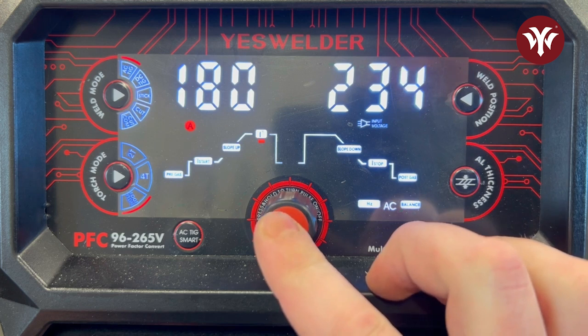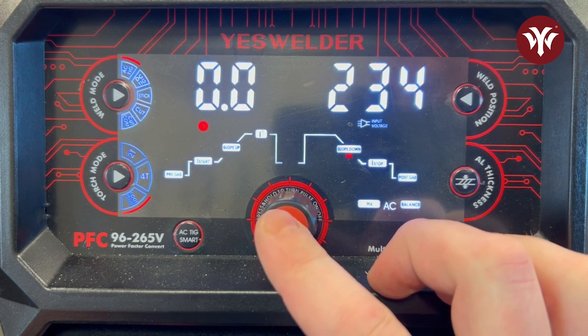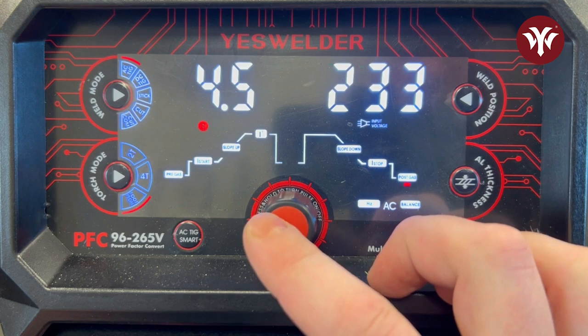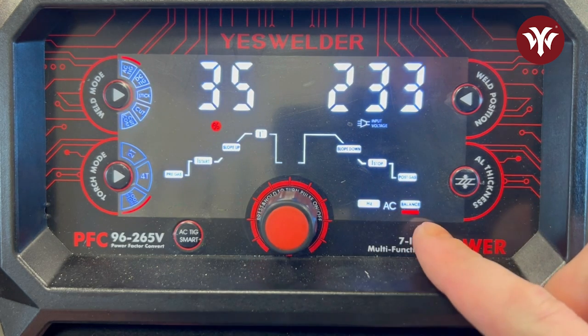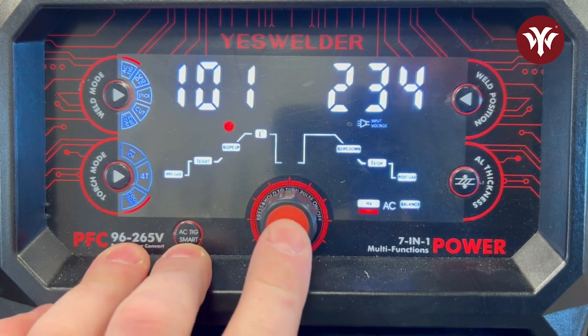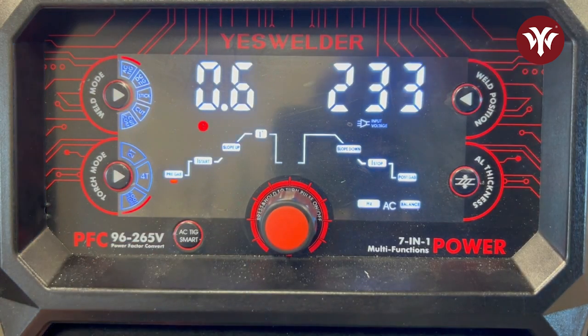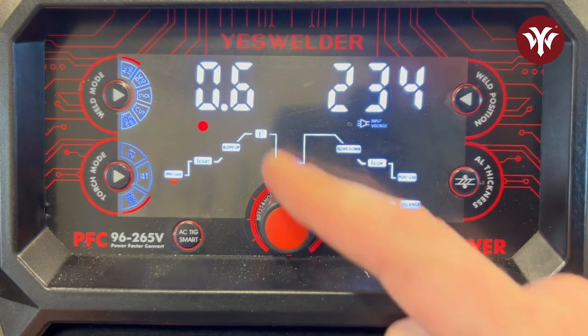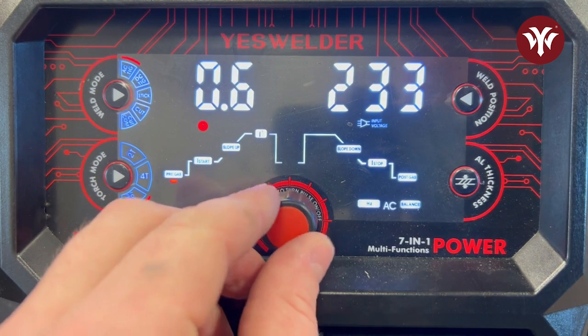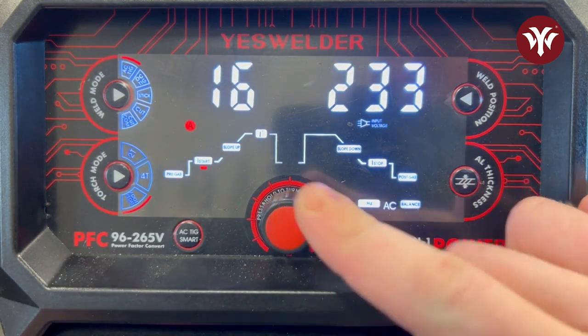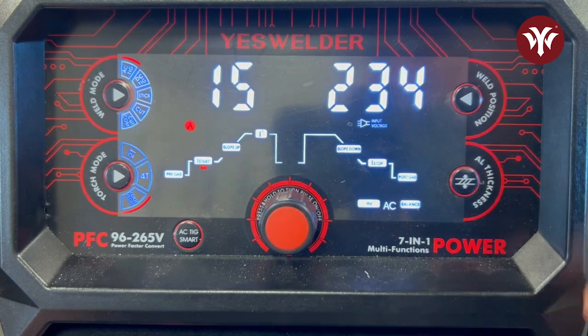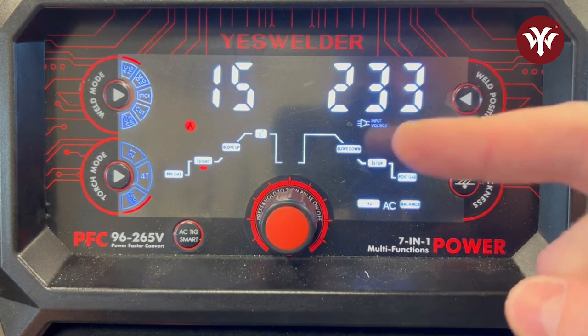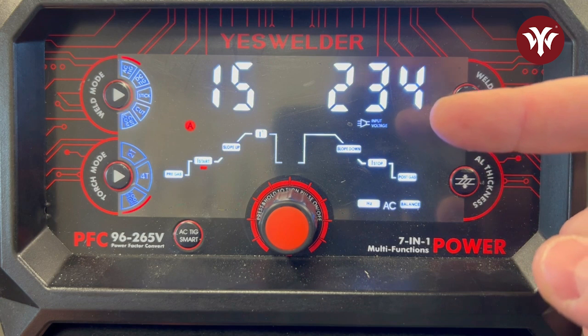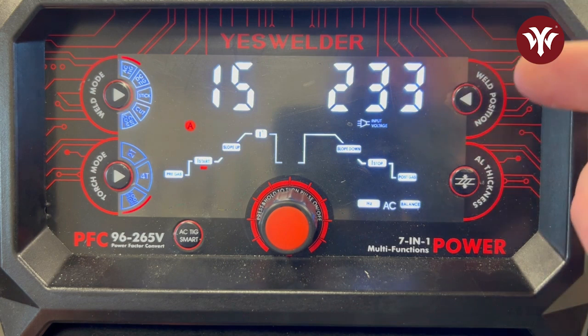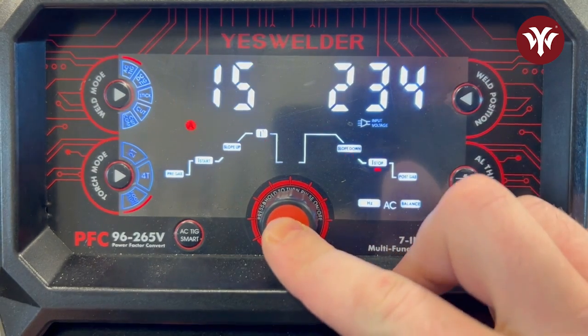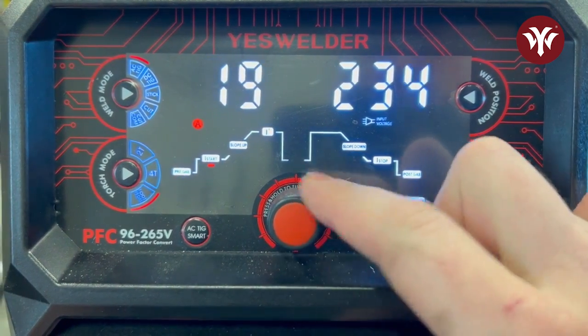And then if you push the button here is where we're going to go through the slope down, I stop, post gas, balance, frequency. So we're going to get to pre-gas. So I'm going to leave it set at about half a second. Starting current is 15 amps. If you are welding really thin material, you may need to lower that. If you're having a hard arc start on materials potentially thicker, oops, I guess it goes through the menu. Let's get back to I start. You could turn that up.